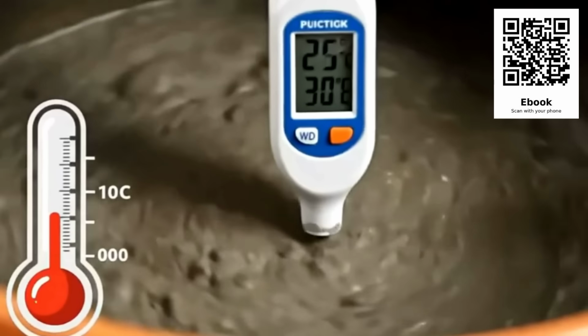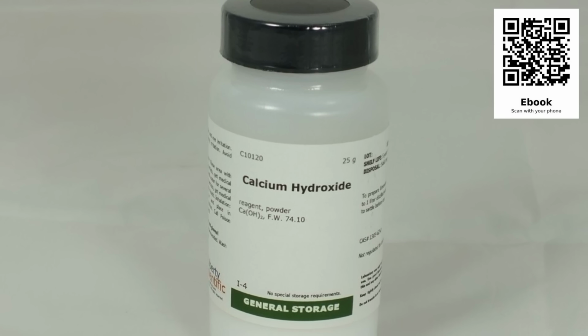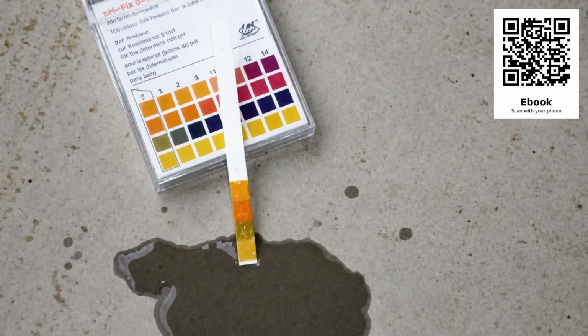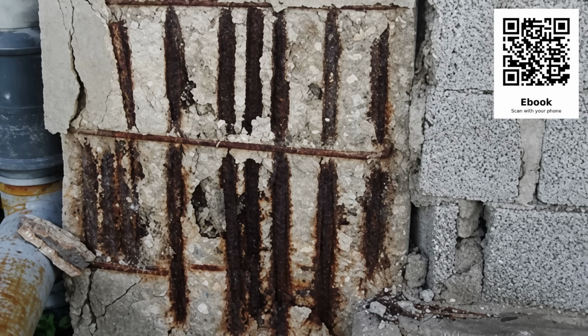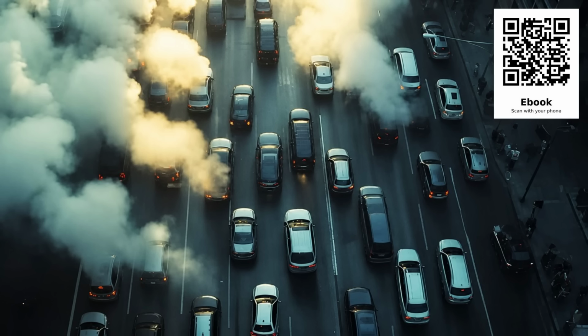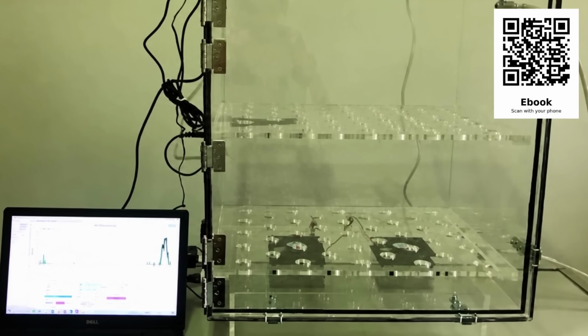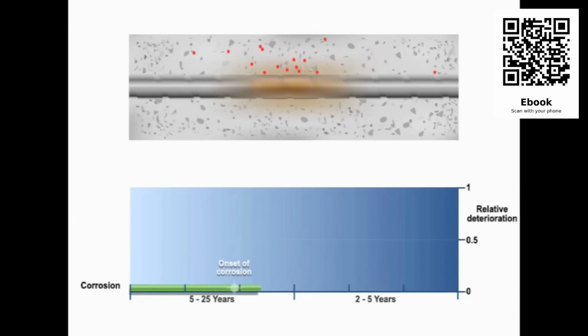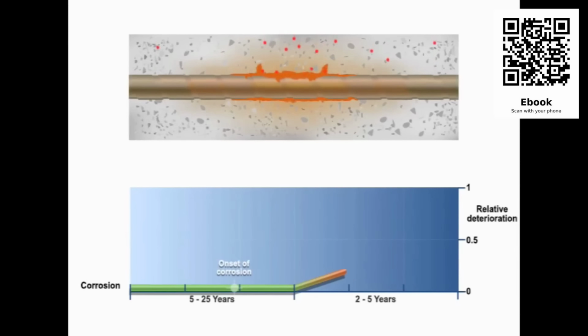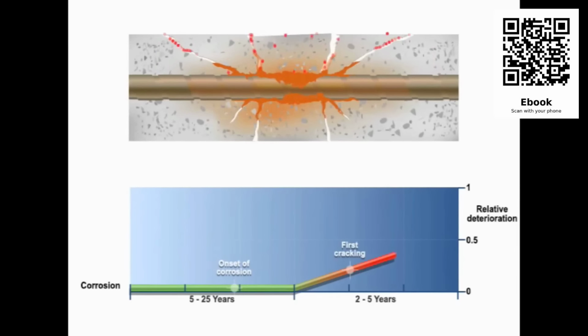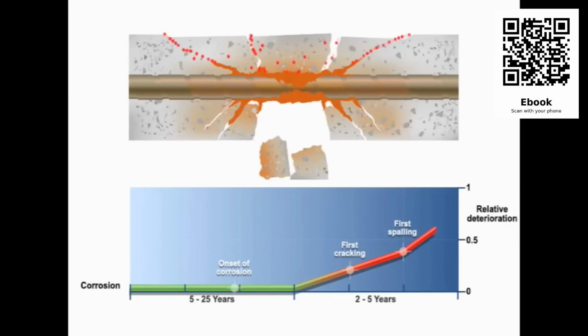This reaction releases heat. It also releases calcium hydroxide as a byproduct, which raises the pH of the cured concrete to around 12 or 13. That high pH is what protects steel rebar from corrosion in reinforced concrete. But it is also what makes concrete vulnerable to a process called carbonation, in which atmospheric carbon dioxide slowly converts that calcium hydroxide back into calcium carbonate, lowering the pH and eventually allowing rebar to rust.